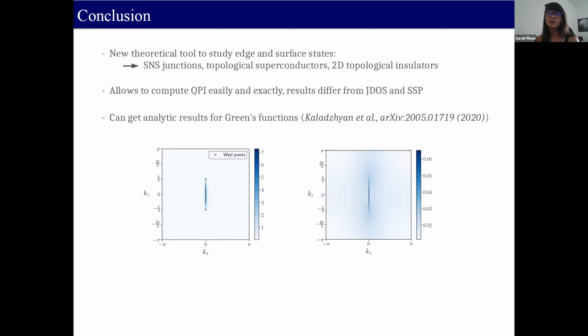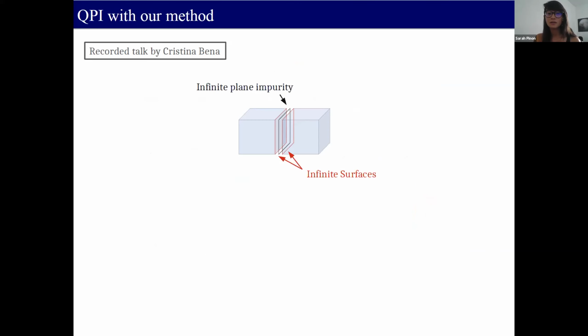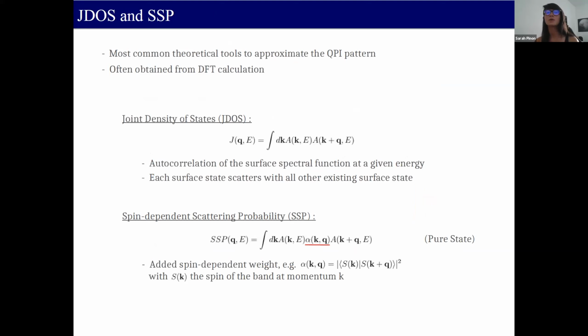So it is known that JDOS and SSP, as I showed in the mathematical expressions, are approximations of the QPI pattern. What you need to compute is the Fourier transform of the local density of states, and this is not what they compute. They compute something that depends directly on the surface spectral function, and it's an approximation. So things are lost when you compute these quantities that you don't lose if you compute the Fourier transform of the LDOS directly. In particular, some things about the spin structure can be lost. For example, if you only take JDOS and you don't take SSP, you have no information on the spin structure because you don't consider whether the states scatter depending on their spin or not.